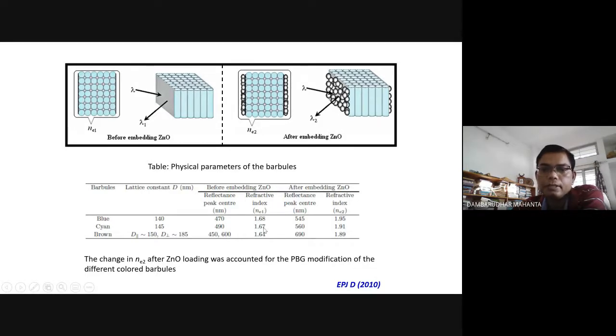So the modified refractive index, we calculated before embedding and after embedding. After embedding, you see there is a change, because now lambda is shifting: before embedding you get lambda 1, and after embedment it will be lambda 2, it cannot be lambda 1. Know that these nanoparticles are grown on the top surface, they have not been infiltrated into the system, otherwise the system will be damaged. So we are keeping the system as it is, only on the keratin layer these nanoparticles have been grown. So it is going from 1.68 to 1.95. In the cyan case 1.67 to 1.91, and in this case up to 1.89.